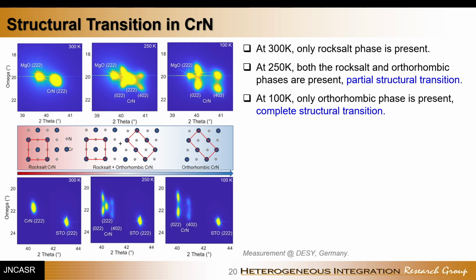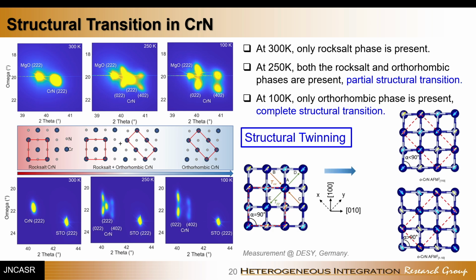As you reduce the temperature, this basically splits into two: a first peak and a second peak. And these are basically orthorhombic grains. Basically, this is the orthorhombic transition. What is even more interesting is that it's not just two splitting. Each of the two peaks also has a further split because of something known as structural twinning in the system.